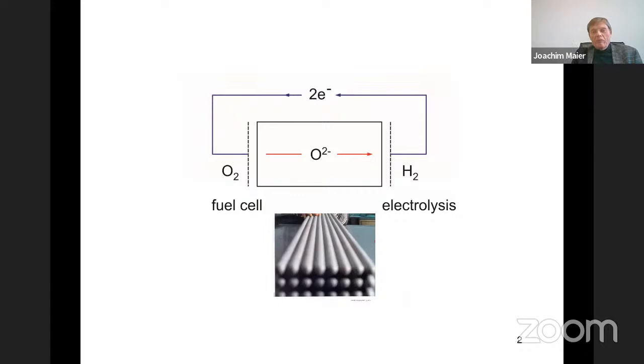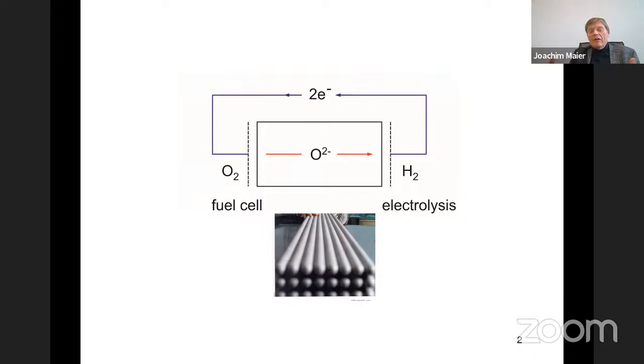This is a typical device in solid state electrochemistry. In the middle you see an oxygen ion conductor — a ceramic zirconium dioxide — which at high temperatures converts hydrogen with oxygen to water. In addition to the electrolyte, we have solid electrodes that are not only ion conductors but typically ion-plus-electronic conductors, and then other materials like leads that are electronically conducting. The major goal is to control charge carriers in the solid state.